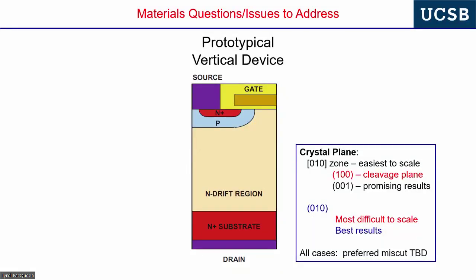And then fine, so you roll a dice and you start picking some planes, and all of them have a different personality in epitaxial growth, okay? And then it gets worse, okay? And I spent a lot of my career on this, okay? When you finally select the best crystal plane, usually the metric is sustaining planar morphology during growth. Even better, step flow growth or layer by layer growth.